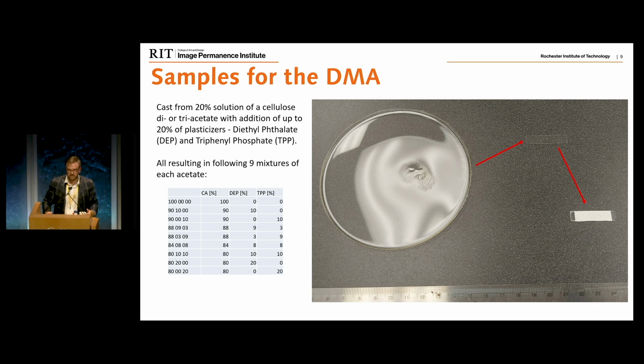So we have 9 compositions of each, and they depend on the proportion between the acetate and 1 or 2 plasticizers. And then those casts are cut for the DMA. Those are cut into thin strips, 30 millimeters long, 8 millimeters wide. And some of them are painted with historically accurate paint from the recipe from Disney Archive.